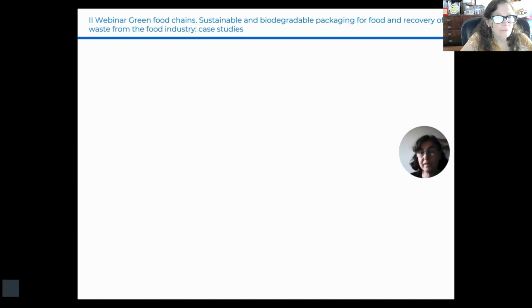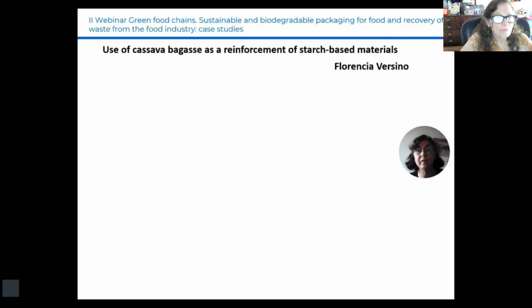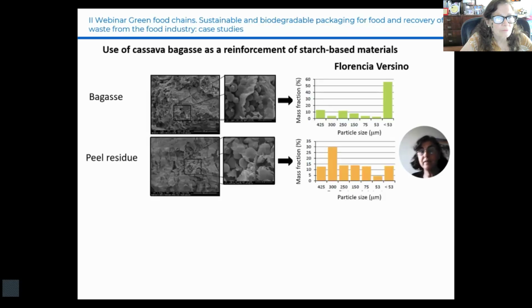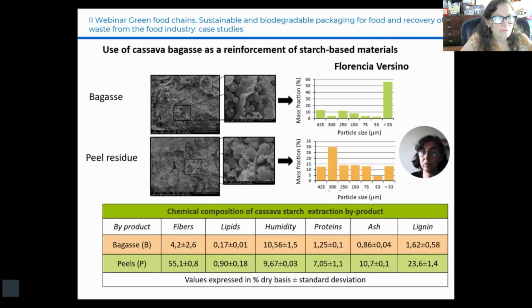As part of Dr. Florencia Versino's doctoral thesis, we studied the use of cassava starch extraction byproducts, specifically the bagasse and remaining peels, as reinforcement for cassava starch-based films. We characterized the byproducts by studying their morphology and particle size distribution using scanning electron microscopy. We also determined their chemical composition, observing that the peel residue is a source of lignocellulosic fibers, while the bagasse contains starch granules remaining from the extraction process, as seen under the same observations.